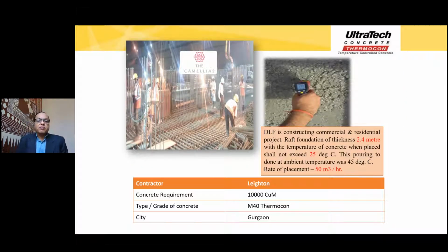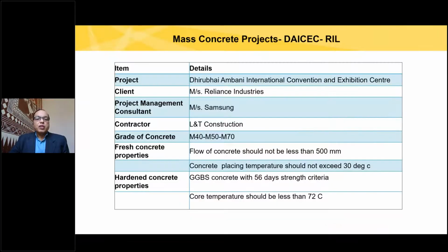You can see here, in this project, about 10,000 cubic meter was used. This is the DLF project again in Gurgaon, where the concrete used is M40 Thermocon, that is temperature controlled concrete. Here again in this project also, the thickness of the raft foundation was 2.4 meters, and the temperature of concrete when placed should not exceed 25 degrees centigrade. So a very similar kind of condition in this project also.